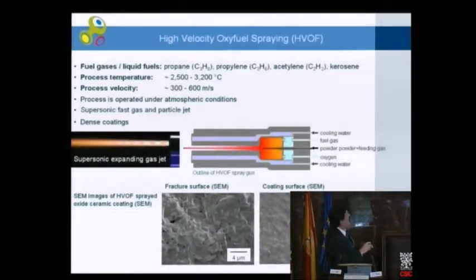In contrast to that, the supersonic flame spray. And you can see with a higher resolution, this material looks much more like a hot isostatically pressed or a sintered ceramic. There are no more lamellas. And one of the reasons is that we have a much higher kinetic impact, giving much denser and better adhering coatings, but the drawback is, to a certain extent, the limited process temperature. So we cannot process any type of ceramic, so there are some limitations, for example with zirconia and its blends.